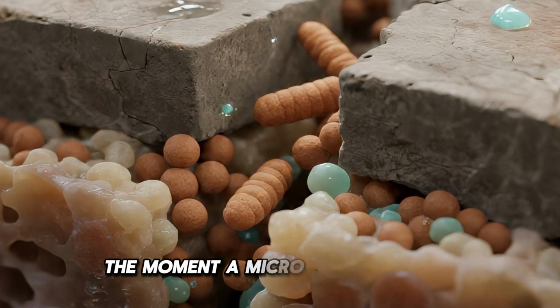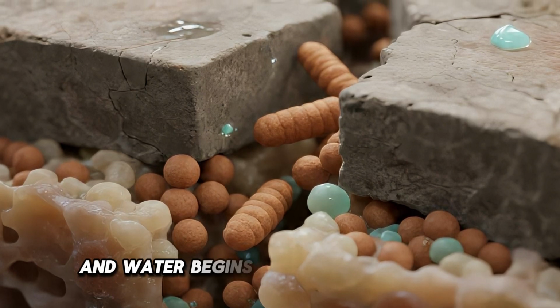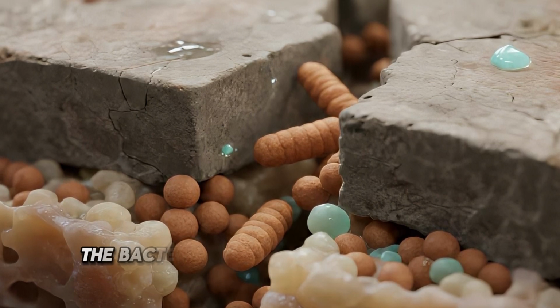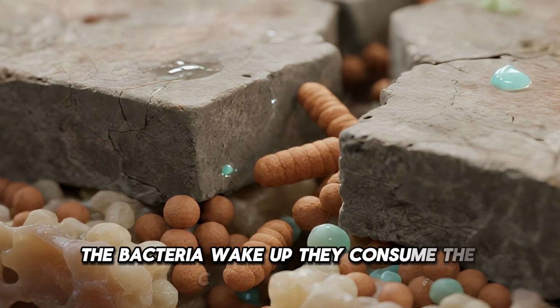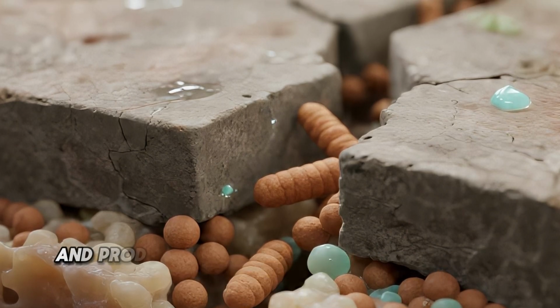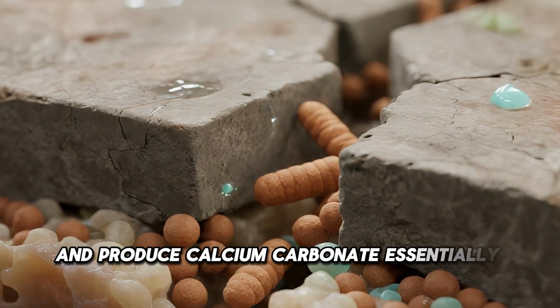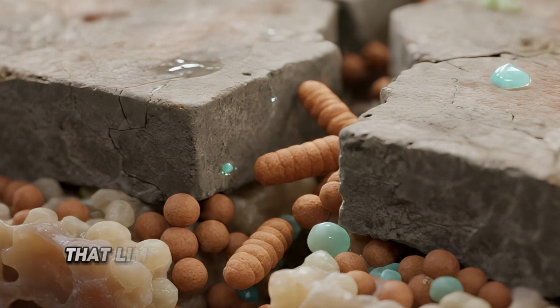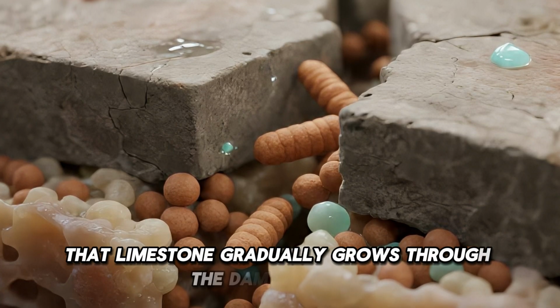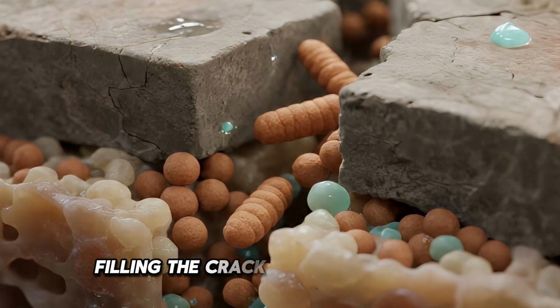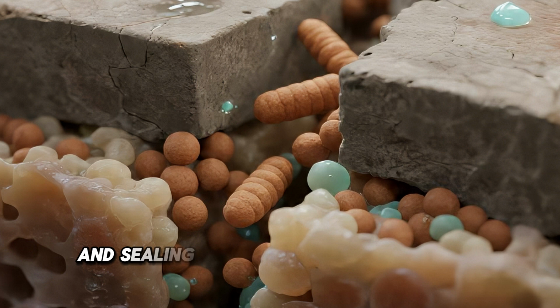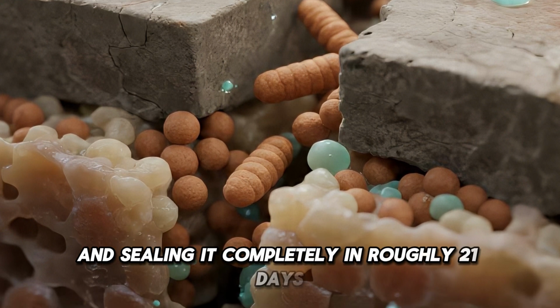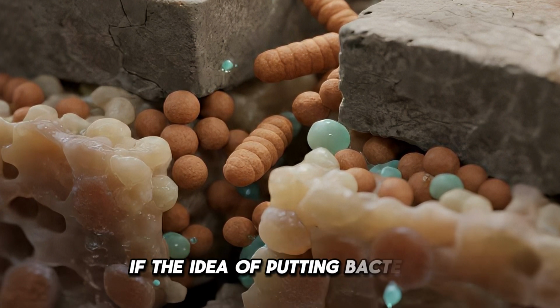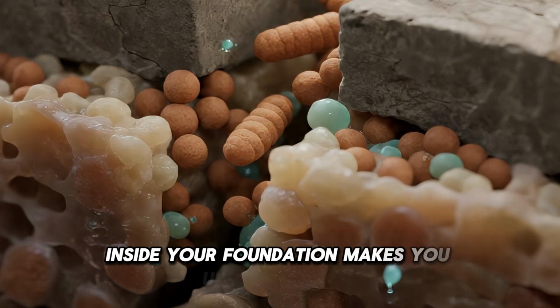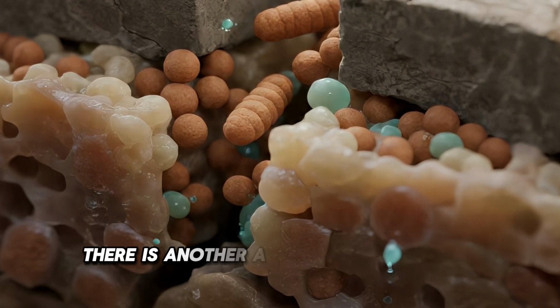The moment a microcrack appears and water begins entering the concrete, the bacteria wake up. They consume the calcium lactate and produce calcium carbonate, essentially limestone. That limestone gradually grows through the damaged area, filling the crack from the inside out and sealing it completely in roughly 21 days. If the idea of putting bacteria inside your foundation makes you uncomfortable, there is another approach.